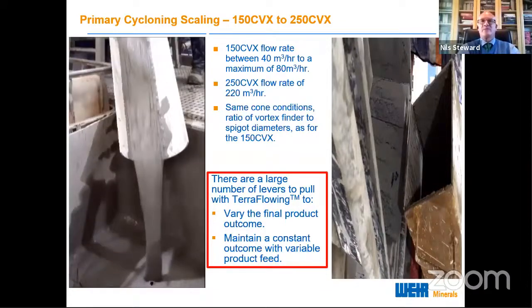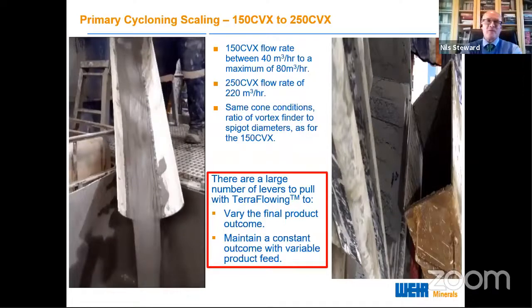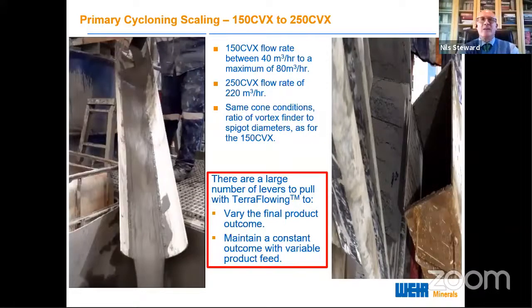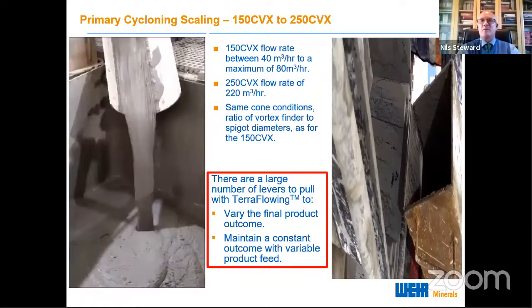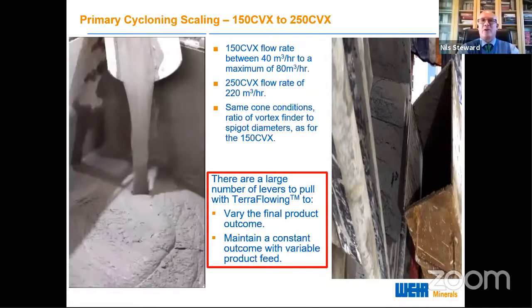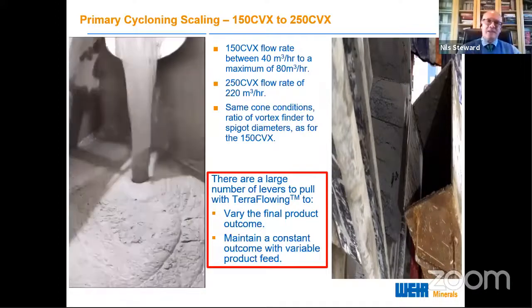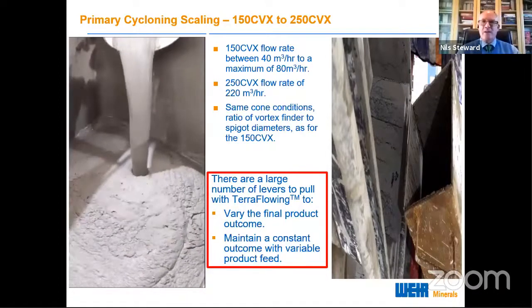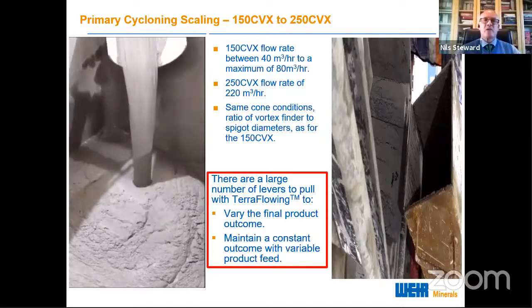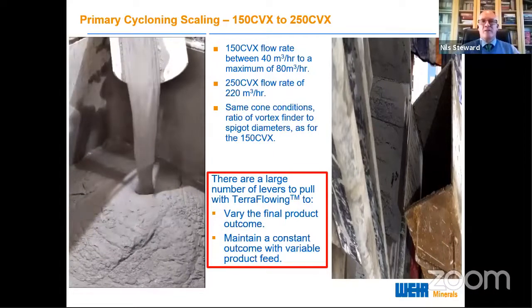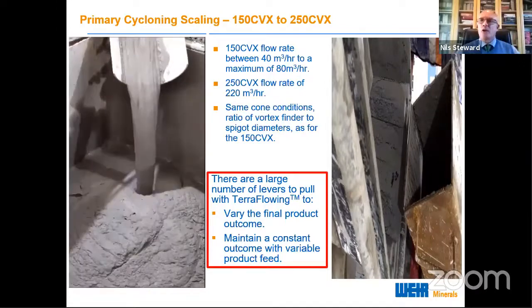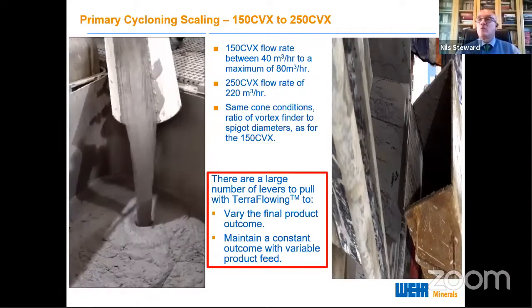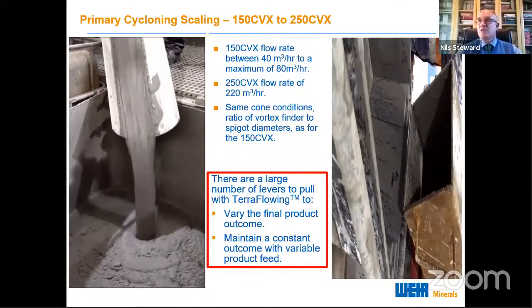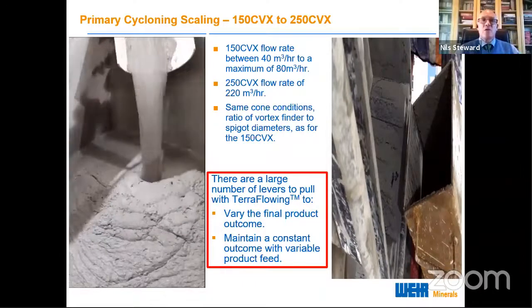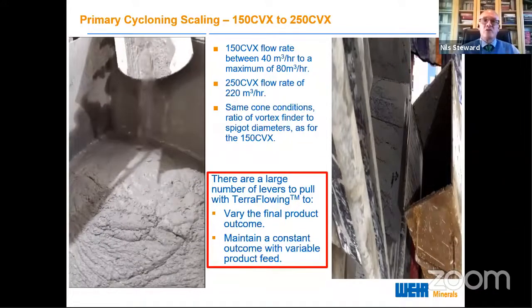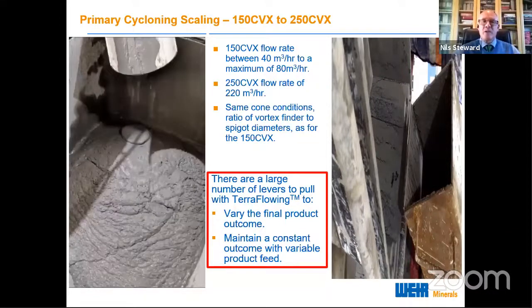Now, the problem, obviously, with the test work in a 150 millimeter cyclone is that we're only getting around 40 cubic meters to 80 cubic meters per hour through this. So if we were going to build a facility to deal with 10,000 cubic meters an hour, we'd have fields of cyclones. So what we've been doing over the period of time we've been developing this is having a look at scaling to larger cyclones. And we have scaled this to a 250 millimeter cyclone with a flow rate through it of 220 cubic meters per hour. And this gives you an idea.